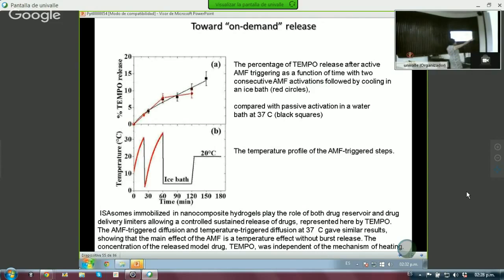If you look first at figure B, what we do here is we raise the temperature, and we did it for almost 20 minutes, the first time. Then you let the temperature drop, and then you do it again, and this time we went about 40 minutes and above 30 degrees. Then we let it come down, and then we have an ice bath. So we only triggered it twice. We pushed the button on, it went up for 20 minutes, then off, and then on again, and then off. The total was about 60 minutes, and then the ice bath.